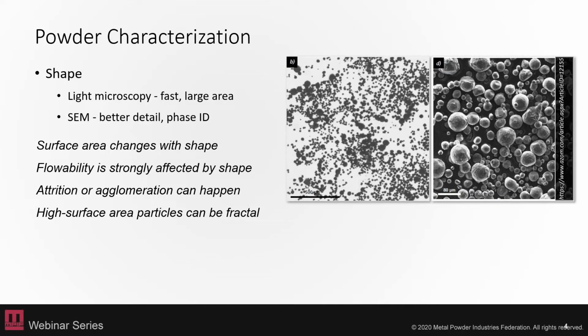And the high surface area particles can be really fractal, such as those off-spherical shapes, and those can catch on each other and agglomerate, or catch on each other and cause lower flowability, or even catch on each other and break off small pieces and change your size distribution, and simultaneously change your shape. So these are impacts that would affect your quality and your handling.